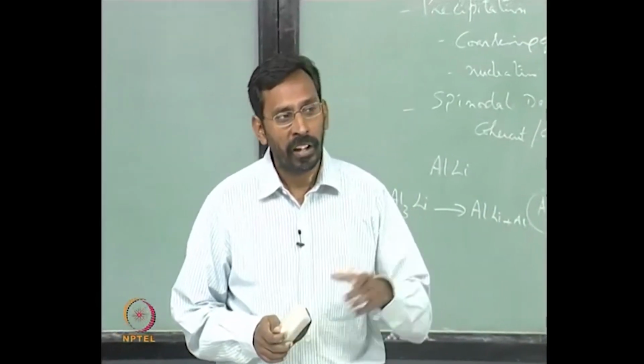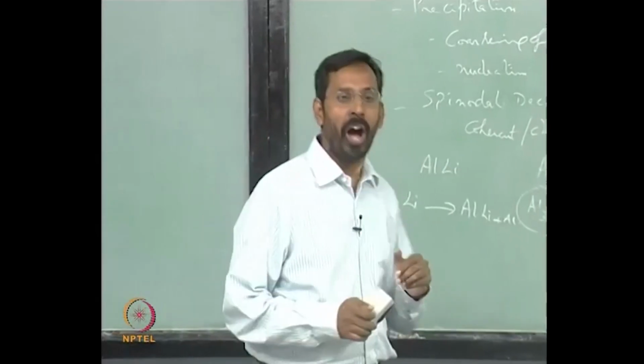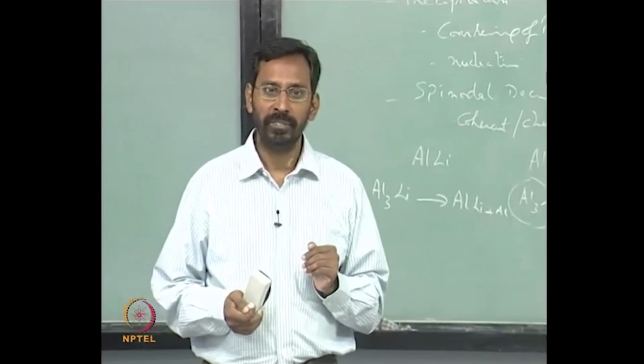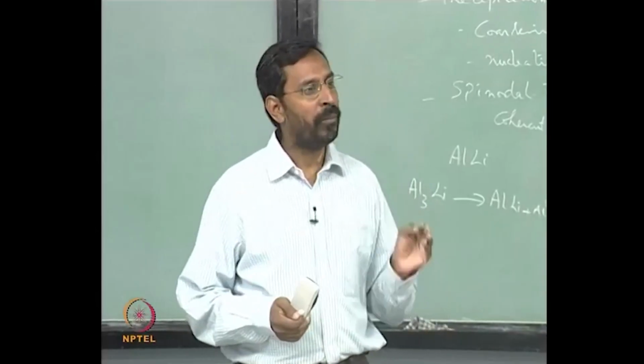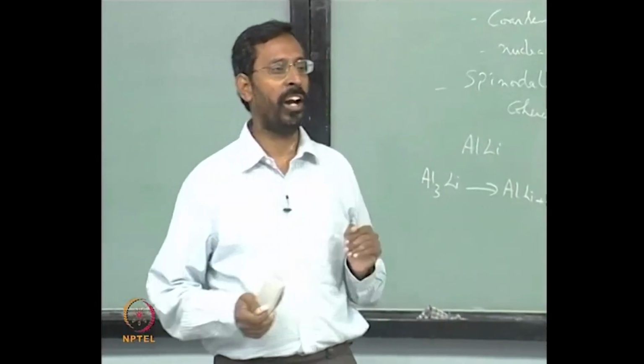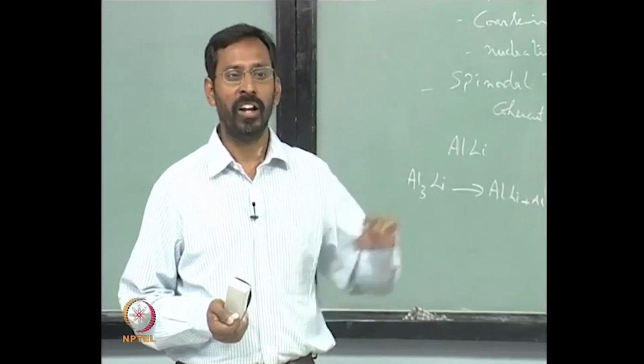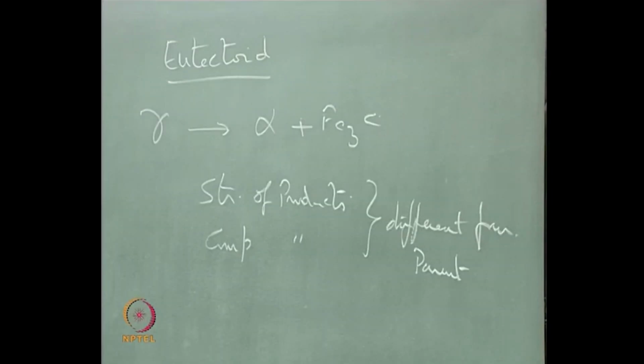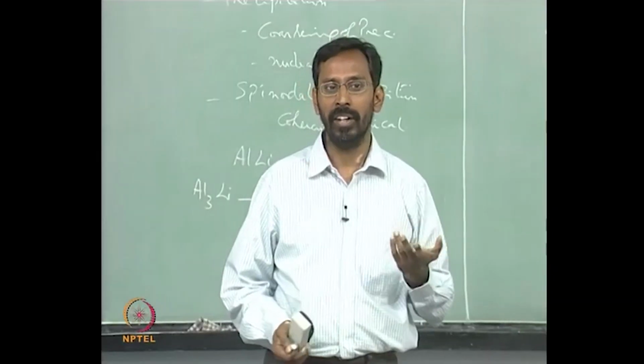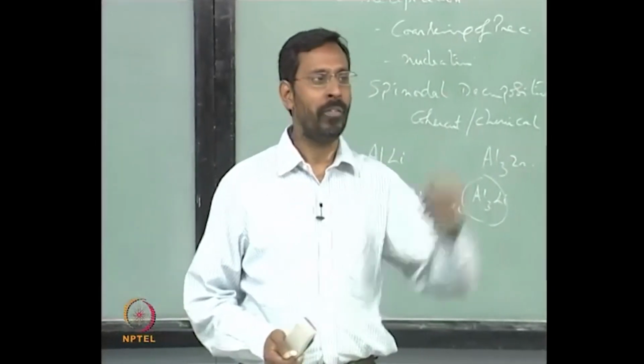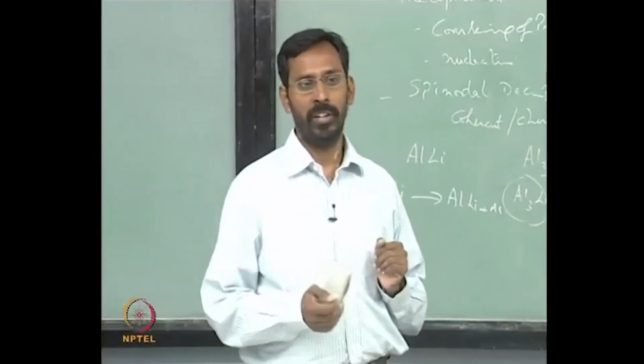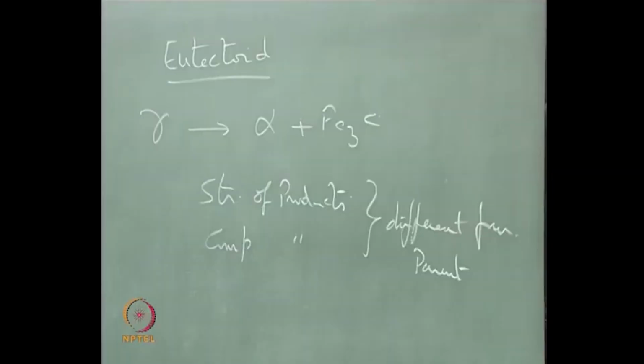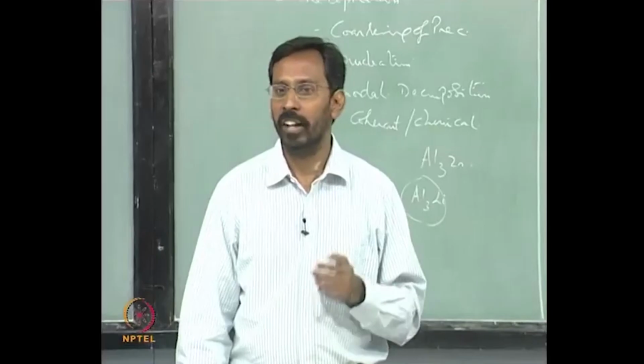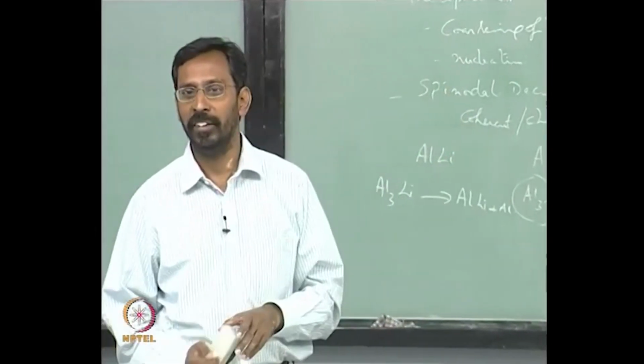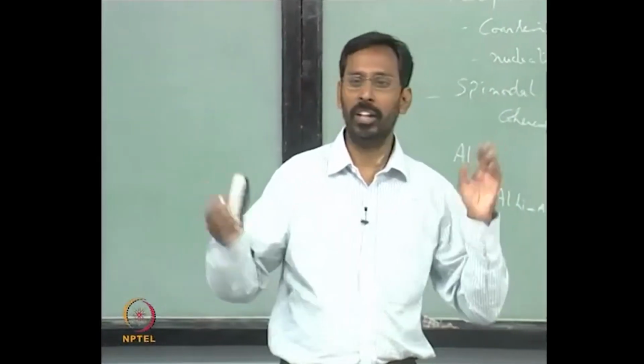Having the nucleation having the same structure. Yeah, one way is to have certain nuclei already available. When do I have such nuclei already available? If I am choosing an alloy which is hypoeutectoid or hypereutectoid. Once I choose compositions which are hypo or hyper, that means one of these two phases is already there inside the structure, obviously. So in a hypo you have alpha that already forms, ferrite forms from the austenite. In case of hyper, cementite forms from the austenite. So before you reach the eutectoid, you already have one of these two phases already being present. So that phase which is already there can nucleate this, and as a result the activation energy can be lower. But if I am choosing the eutectoid composition exactly, I do not have this choice with me. There is nothing before, the only thing that is before is austenite.